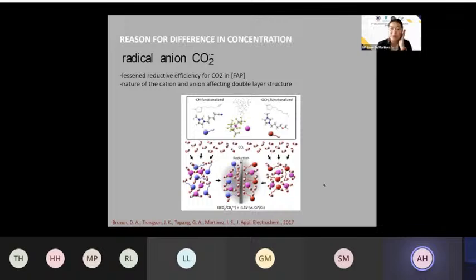This is what we think the reason is for the difference in concentration between electrochemical measurements and, of course, the bulk. Like I said, a reduction has to be done to measure the amount of carbon dioxide in the electrode. Therefore, we need to really find out how to measure the radical anion generated in our electrodes, and this could lead to less reductive efficiency of our carbon dioxide in the ionic liquid, and of course the nature of the cation and anion affecting the double layer structure, which in turn of course affects how the electrochemical process measures the amount of carbon dioxide present on the surface of the electrode.